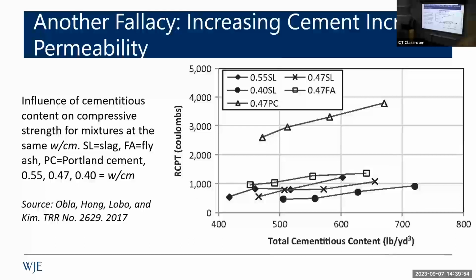So getting paste out of concrete is not only good from a carbon reduction standpoint. I started advocating for this back in 1998 for durability, right? The more paste we put in, the more alkalis, the more chance we have alkali-silica reaction. The more paste we put in, the more shrinkage we get, the more restraint cracking we get. It costs more. So why do we put more paste all the time in our concrete? And the reason is control. The reason is with more paste, a ready-mix producer can have their moisture levels fluctuate with less impact on the water cement ratio, and therefore less impact on strength.